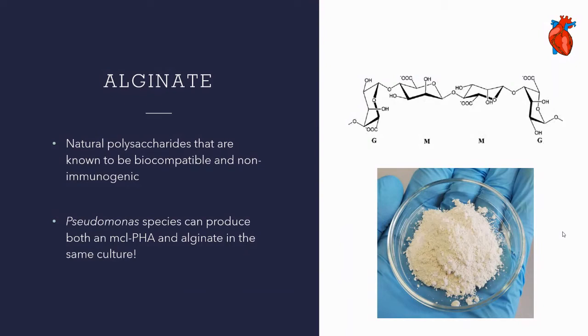So some initial results that I would share with you today. Firstly, some cytotoxicity results. Using C2C12 mouse myoblast cells, I firstly looked at a resazurin assay to compare tissue culture plastic to both my PHA and also alginate with various crosslinkers. And what I found was that my polymer actually performed better than TCP after days 3 and 7, and the alginate, whilst it didn't perform quite as well, was not significantly worse.